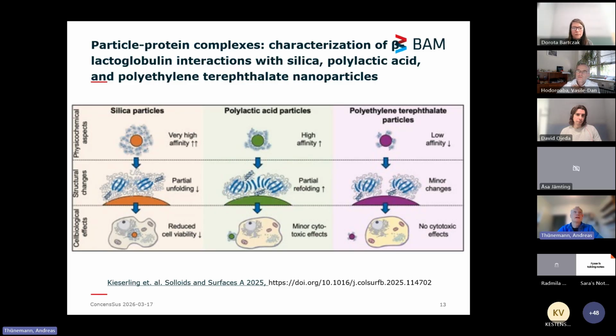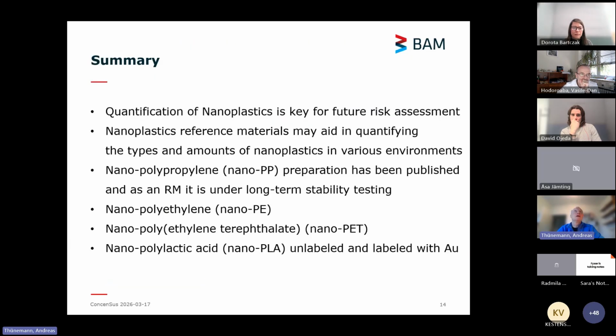there's a strong unfolding of the protein, and this seems to produce a low cell viability. With the polylactic acid particles, the refolding of the lactoglobulin is low, and there are only minor effects. And for the protein on the polyethylene terephthalate particles, we see minor changes in the structure of the protein and no cytotoxic effects. So that means depending on the particles, the possible toxic effects are very different. And at the moment, we have submitted a paper where we use the same method to investigate how enzymes change their activity when they interact with nanoplastics.